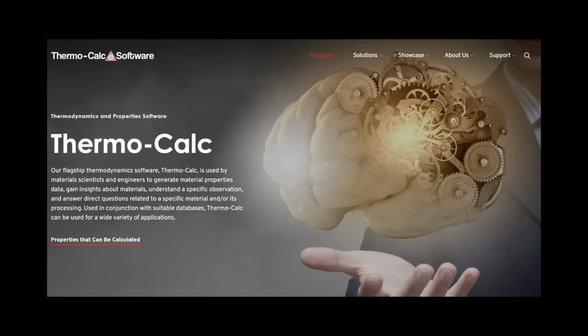Just before we go any further, I just want to touch on that modeling software. For those of you out there, Larrin has access to this software where you put in a steel chemistry and it'll show you what changes happen at different temperatures, or whatever you really want to look at. Yeah, it will predict equilibrium compositions of phases and amounts of phases. That's a little bit complicated, but it tells you if you take a steel of such and such composition, heat it up to 1900 degrees and hold it there for infinity, you'll have this much carbide, this much carbon in solution, this much chromium in solution. And you can use that to predict various things.